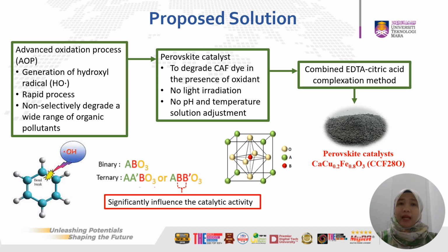Advanced oxidation process has been broadly used as a water or wastewater treatment method due to the generation of the hydroxyl radical, which can rapidly and non-selectively degrade a wide range of organic pollutants. So in this work, perovskite catalyst has been utilized as a heterogeneous catalyst to degrade caffeine from the aqueous solution in the presence of hydrogen peroxide without the need of light irradiation and no pH and temperature solution adjustment.